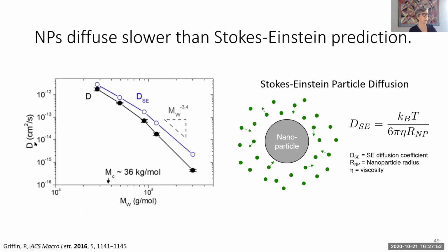So here's the data. This is the diffusion coefficient now as a function of molecular weight. And as you suspect, as the molecular weight of the matrix increases, the diffusion coefficient decreases because you're increasing the viscosity at a fixed temperature. And then for comparison here, I put the blue data, which is calculated from the Stokes-Einstein equation. So the Stokes-Einstein equation assumes that the particle is diffusing just based on random Brownian motion. So just, you know, the monomers are just acting independently and hitting the particle and making the particle move. And so the diffusion coefficient based on Stokes-Einstein has a temperature and viscosity piece, and it depends on the radius of the nanoparticle, right?